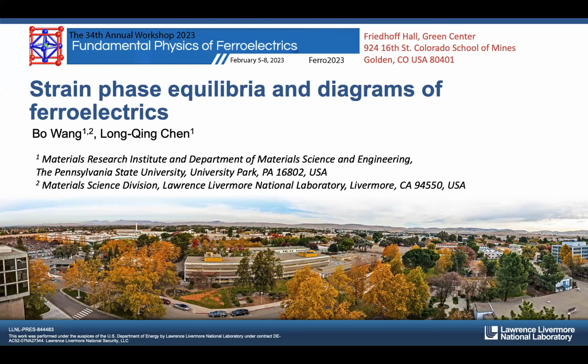In fact, I didn't really mention it here or even in the paper I drafted, but I should. The ferroelectric phase, of course, is denser because it's the high pressure phase, ultimately at 100 GPa. But at these lower pressures, that's not necessarily so. So getting the delta V of the different phases is critical here. And it's a pretty small number, the delta V between one of these phases and another.